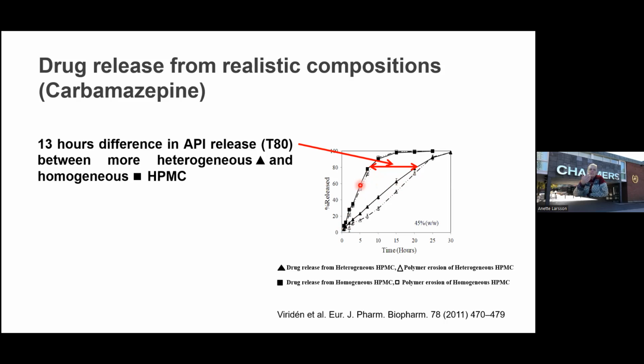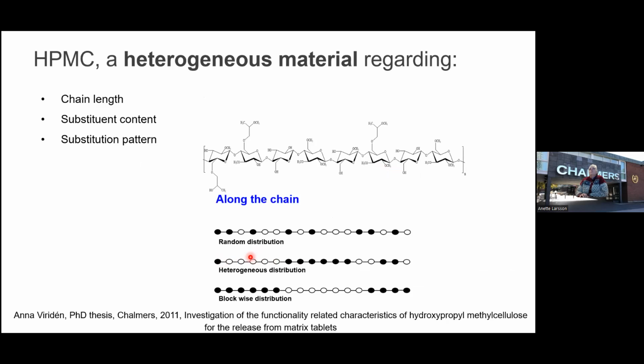What surprised me a little bit is that still, when you buy HPMC, you buy it on degree of substitution and you buy it on viscosity, and not on the substitution pattern, even if we know that this has a huge influence on the drug release rates. So this is a parameter that I think one can develop further. I can also say that the way one determines whether it is heterogeneous or homogeneous is done by using an enzyme that needs, for example, 3 unsubstituted units to cleave. And if they are very random, then that will not happen. So one can then compare how much glucose is liberated from enzymatic cleaving. And that is a similar principle to what people use, for example, for hemicellulose.